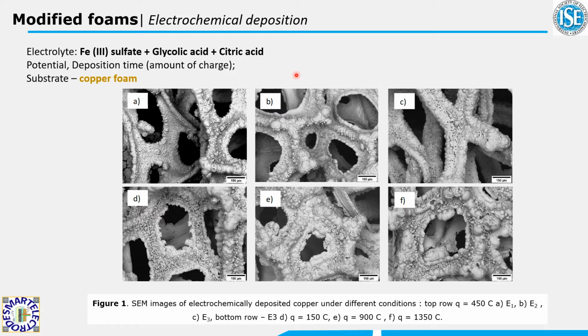On the top row you can see the effects of increasing potential: formation of a more porous and better covered surface. On the bottom row we can see the effect of deposition time. With the increase of the deposition time, or in turn the amount of coulombs, the surface develops more uneven bumps, which could further increase the surface area and in turn the activity of the catalyst.